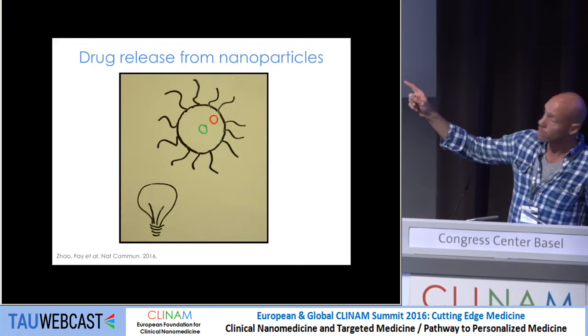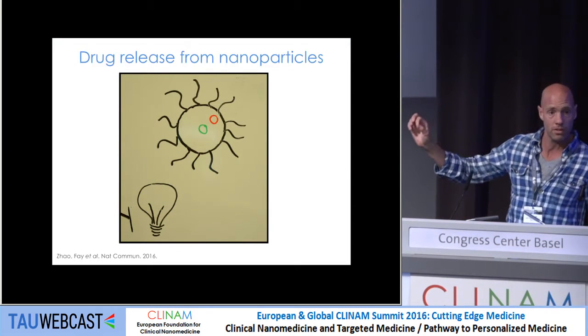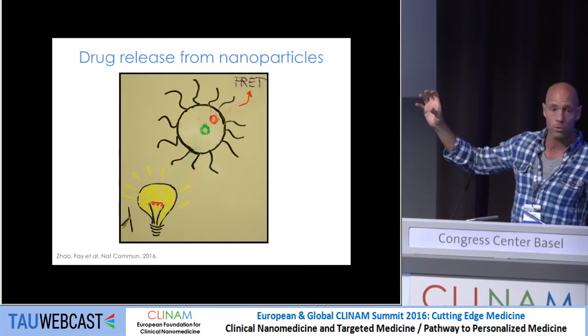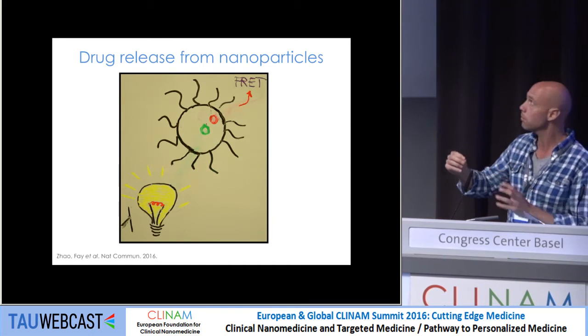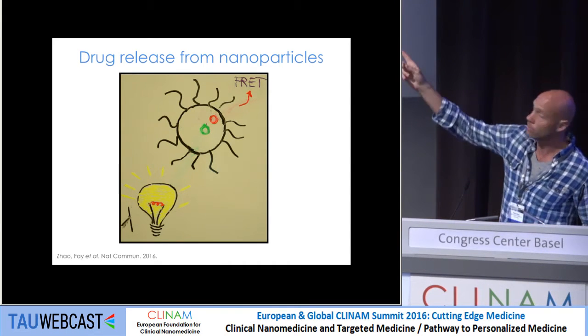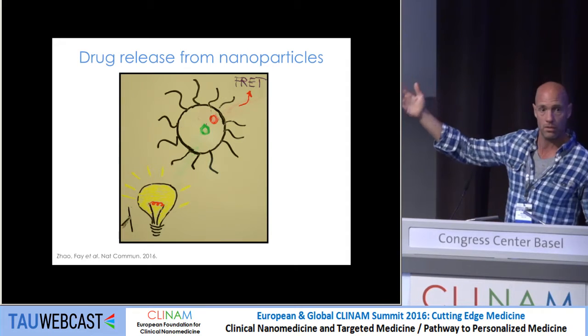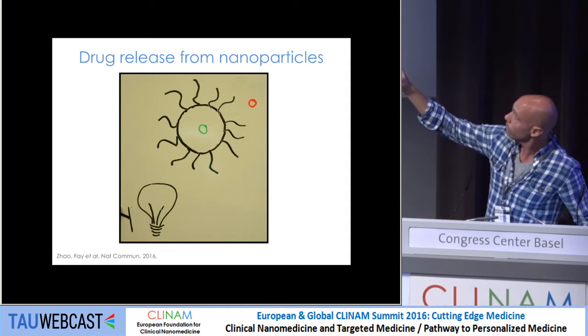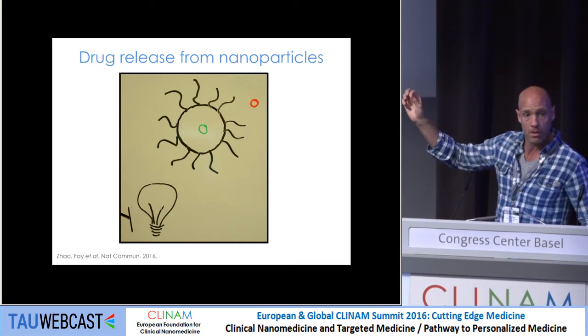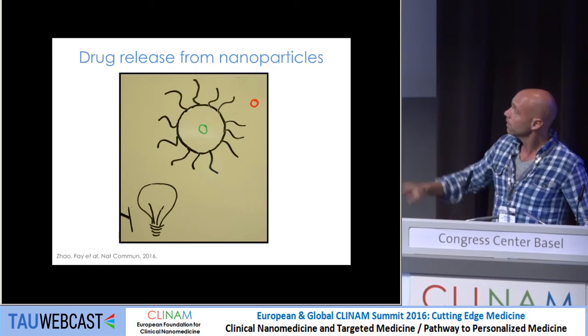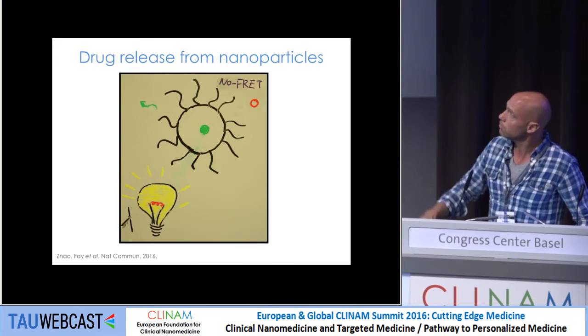We label a nanoparticle with a green dye, and the model drug is the red dye. When they're in close proximity — when the drug is inside the particle — we see energy transfer: fluorescence resonance energy transfer. Once the model drug releases from the particle and we excite the nanoparticle itself, we see the direct emission from the nanoparticle, so there's no energy transfer.